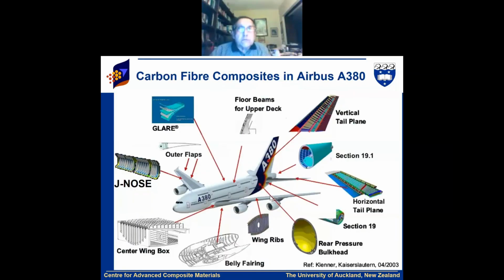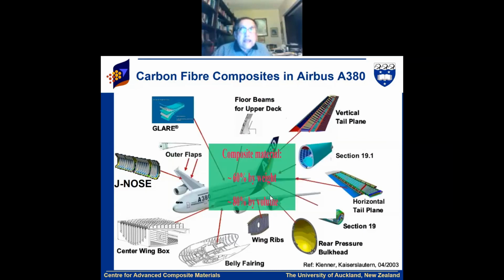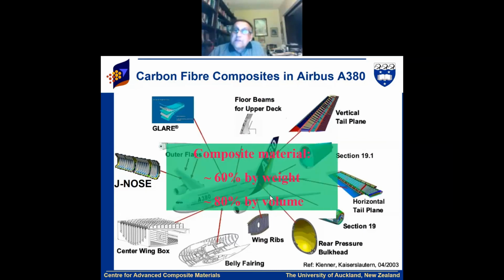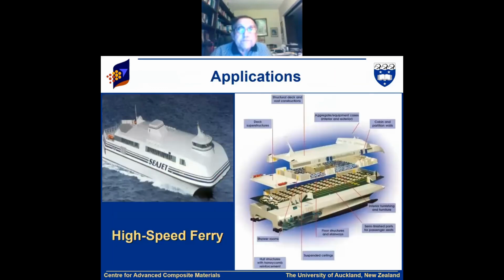And if you go to the A380, unfortunately they'll be stopping; they won't manufacture it anymore. But the science has been sorted out. If you look at that, 60% by weight and 80% by volume were composite materials. The next generation, in fact, was 65 to 70% by weight, so that will be utilized for the next generation of aircraft. Unfortunately, the Airbus 380 will not be manufactured anymore because it was too big and difficult to handle. There are other applications: high-speed boat, high-speed ferry.